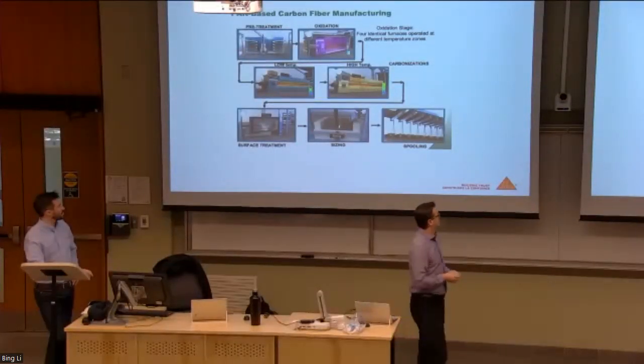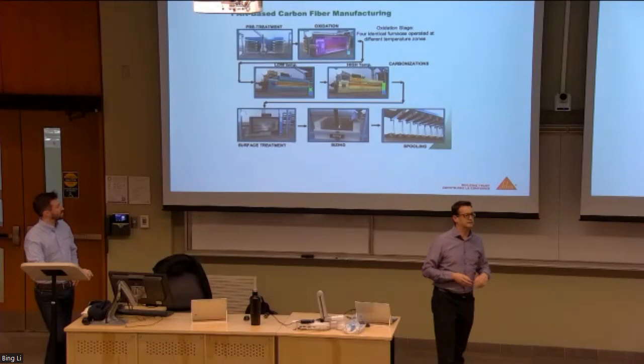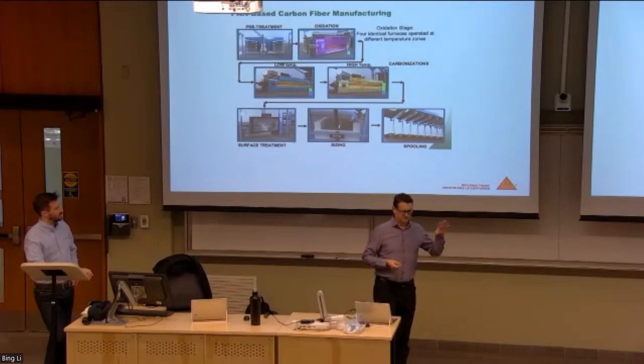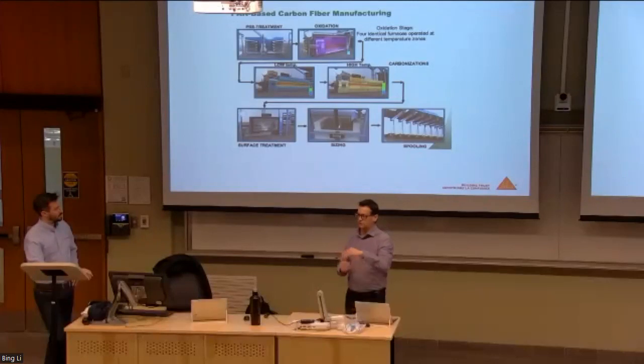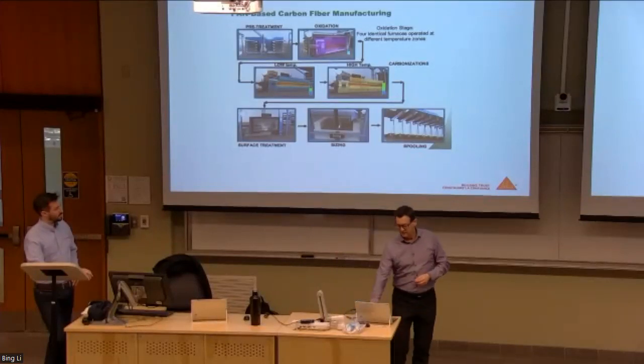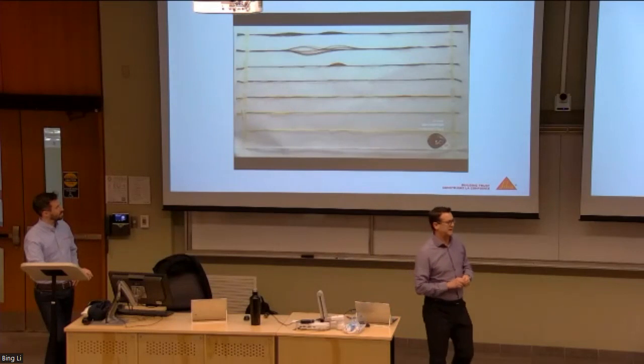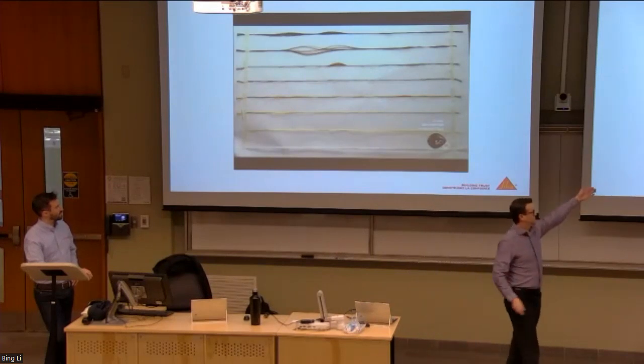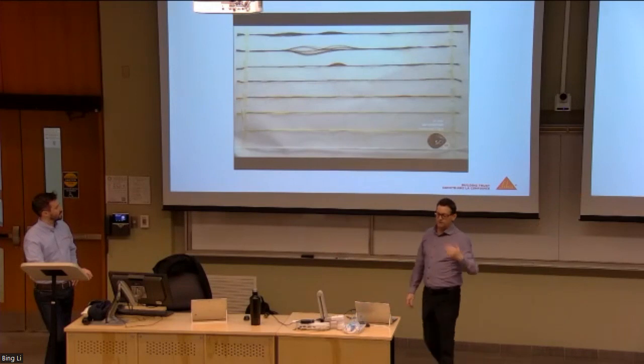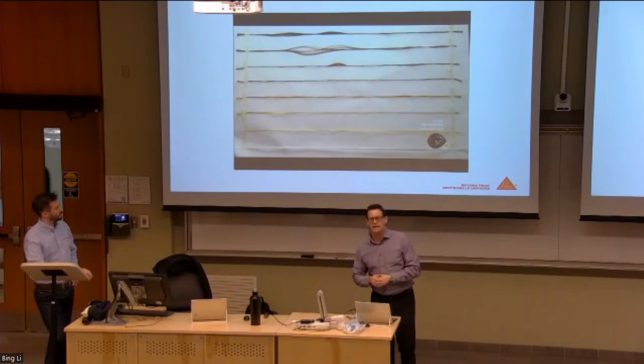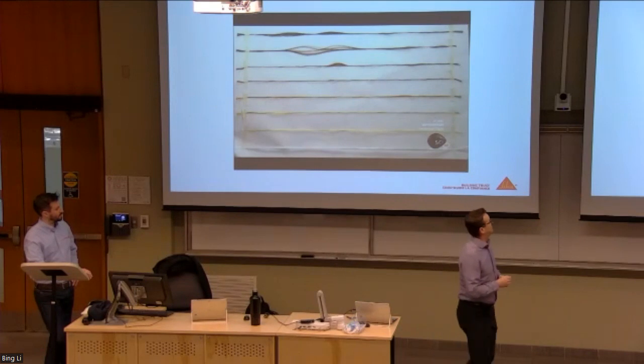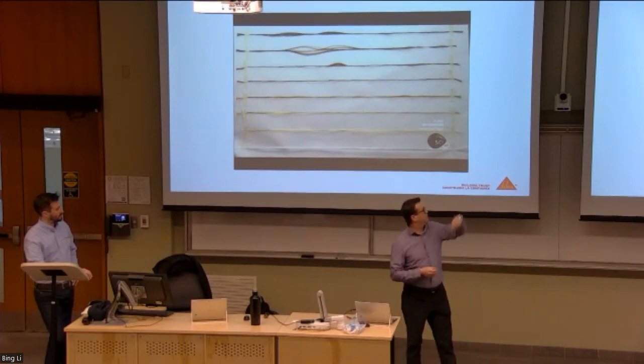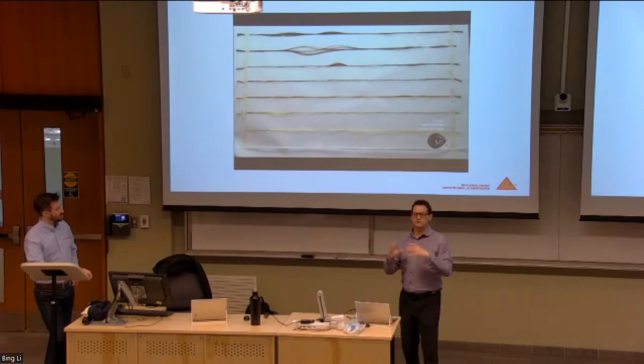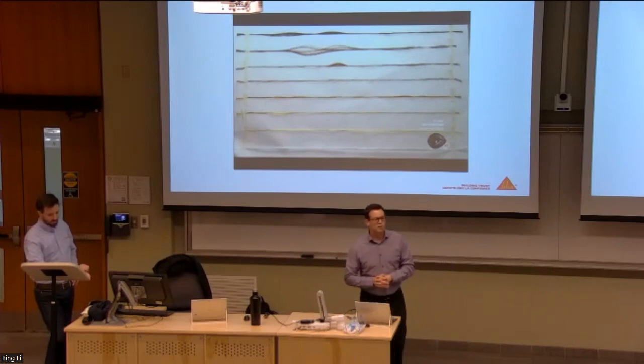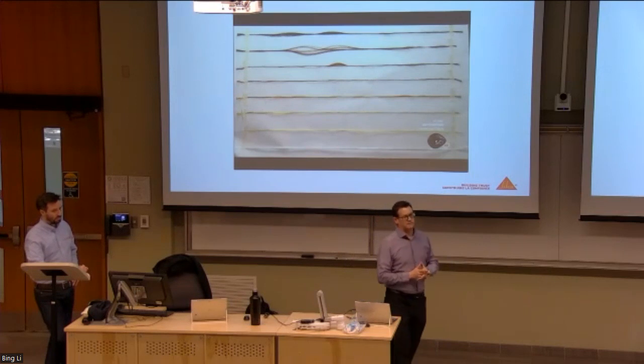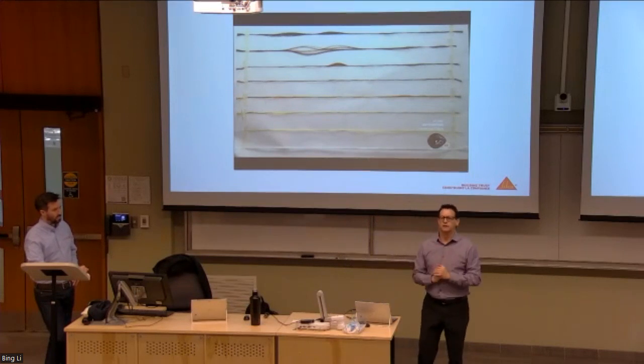Then there's a little bit of processing that happens. They go through a treatment, the oxidation. There are various stages of temperature manipulation to the strand. As it goes through this heat aging process, you start at the bottom with those rovings that I showed earlier, and you work your way up to the characteristic black strand at the top. That's probably just a few hundred of those strands, but once you put these all together in a product, which we'll come to in a minute, there are literally millions of those individual strands running in parallel.